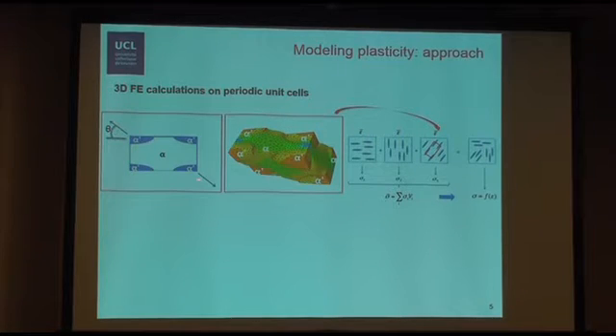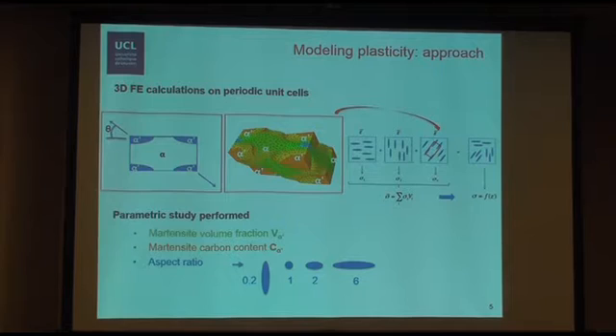And the different orientations are necessary because the real material is mechanically isotropic, the inclusions are randomly oriented. And this is why, to get a global response of the material, an average is made on the responses of each orientation. A more general average is also possible on other parameters, since orientation is not at all the only heterogeneity in the microstructure.